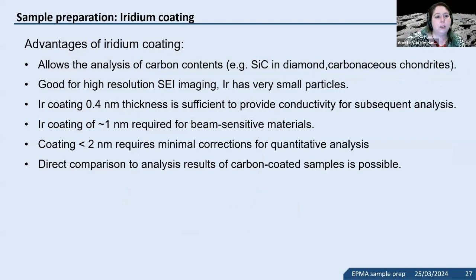People are getting more interested in iridium coating instead of carbon. For quantitative analysis, your standards should be coated with the same material. So that depends then a little bit on the lab if that's an option. But it's specifically good if you want to analyze carbon content. It's good for high resolution imaging, and iridium coating can be applied very, very thin to get good enough conductivity for analysis. And if it's a specific thickness, it has a similar absorption to carbon-coated samples, so then it makes it easier to compare it against carbon-coated samples or standards.